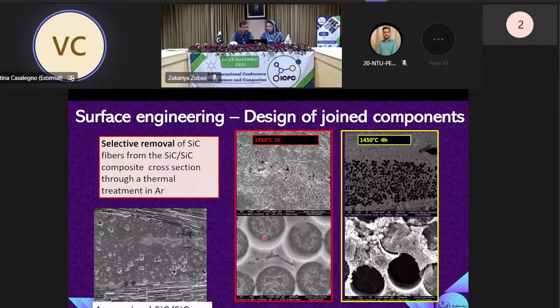And then we were able to tailor the depth of removal of the fibers. And in my opinion, it is clear that for instance, 4 hours in the yellow frame, the removal of the fiber was complete. The treatment was too aggressive. So we tried to reduce the time of the process and obtain just a few microns, let's say less than 10 microns of removal of fibers. And this was sufficient to increase the surface area and to increase the interpenetrating effect of the joining material. I don't know if it is more clear now.